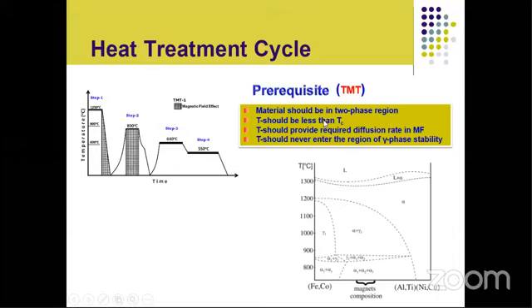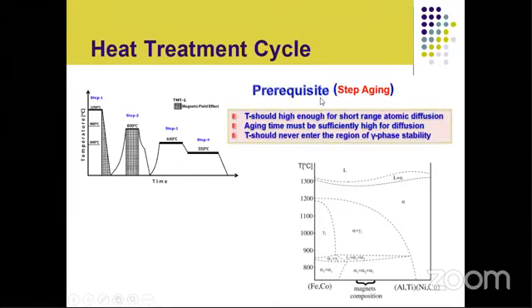Temperature should be less than Curie temperature. It is important. Temperature should provide required diffusion rate in the magnetic field, and this temperature should never enter in the gamma phase, as gamma phase is not good for the magnetic properties. Third step is the step aging. Step aging temperature should have high enough short range atomic diffusion. Aging time must be sufficiently high for diffusion. That is why at these temperatures they are heat treated almost for 24 to 48 hours. And temperature should never enter the gamma phase stability region. That is why this is harmful for the magnetic materials. So if all these prerequisites are managed, then we can get good magnetic properties.